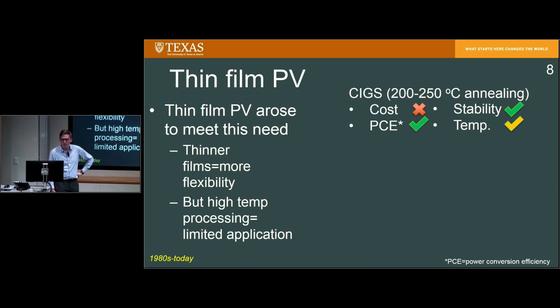CIGS is a little bit more promising, copper indium gallium selenide, which has also arisen as a more recent material to try to meet this need in the thin film community. But even there, you have an annealing temperature of 250 degrees C, which means you need specialized plastics to act as your substrate backing, like polyimides. And that means that cost has been an issue for this material, let alone the fact that just the cost of making CIGS can be problematic as well.